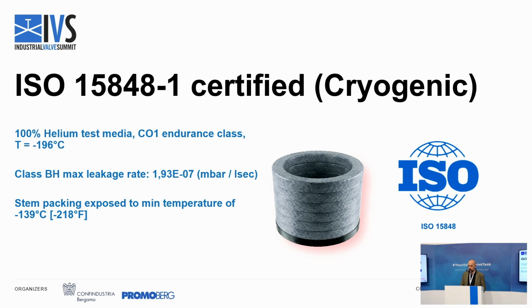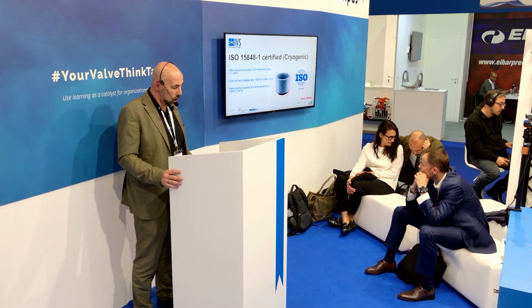Usually in the cryogenic sector, sometimes we have long extension stem, and the compression packing doesn't see that temperature. It works at higher temperatures, so it's easier to achieve fugitive emission performances. Again, we could achieve class BH, but again we had to change slightly the design. We put a carbon graphite ring, dense carbon graphite ring, as a shield for the low temperature and the environment.